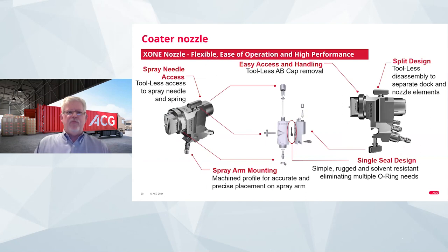Now, the unique aspect of our XONE nozzle is the fact that we've built the nozzle in a split configuration with a docking mechanism and a separate nozzle itself. So the nozzle itself can be easily removed with a single mounting screw that doesn't require any tools. And this also enables the nozzle to be positioned onto the spray arm uniformly each time it's taken on and off of the spray arm. Now, in short, and we'll get into position of spray nozzles a little bit in a few photos, ensuring that your operators can reproducibly position the nozzles on the spray arm, batch to batch between each cleaning cycle, is also a critical aspect to ensuring a uniform process.